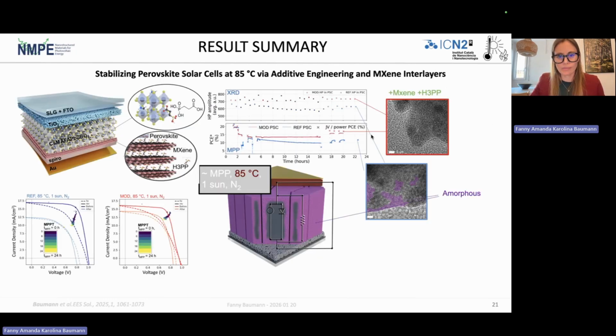So finally, just to summarize again, the loss of the crystalline perovskite material was responsible for the loss in performance in the perovskite solar cells without any stability modification. But with the addition of 3-phosphonopropionic acid that resides in the grain boundaries of the perovskite layer, and also delaminated MXene flakes with functionalization that provide a relaxation barrier between the perovskite and the spiro HTM, we could really see an improvement in stability at 85 degrees Celsius and 1 sun illumination.